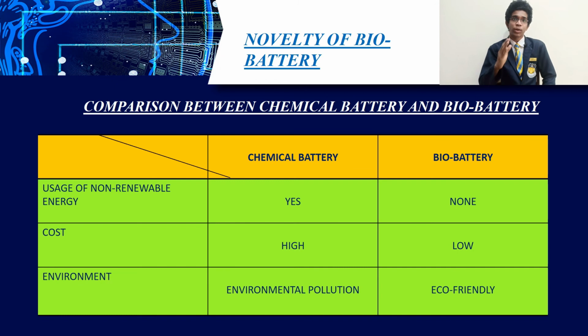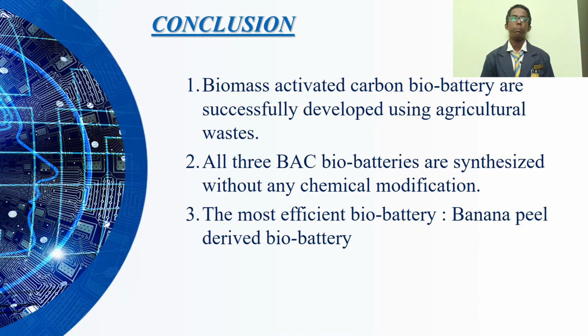The significant advantage that BAC biobattery has in comparison to other batteries is that it is a source of renewable energy obtained at a low cost and is environmentally friendly. The finding of the BAC biomass derived from agriculture waste has the potential to be utilized as a biobattery source to generate electricity, proven by power density and current density measured corresponding to values of 6.6 microwatt per centimeter square and 48 microampere per centimeter square respectively.